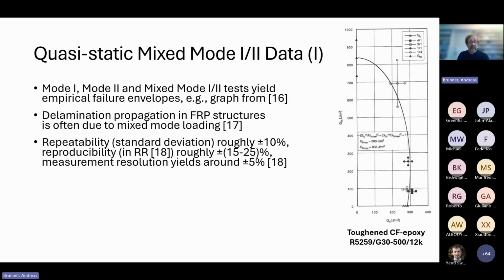And on the other hand, from round robins and tests, we know that the repeatability, which is basically the data from one lab in terms of standard deviation, are roughly something like plus minus 10%. For mode 2 and mixed mode, it can be a little bit higher. And the reproducibility, if you look at round robin tests performed at several labs, then we end up with somewhere between 15 to 25%.